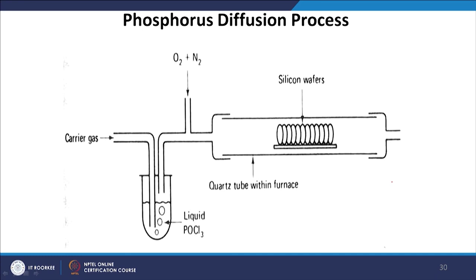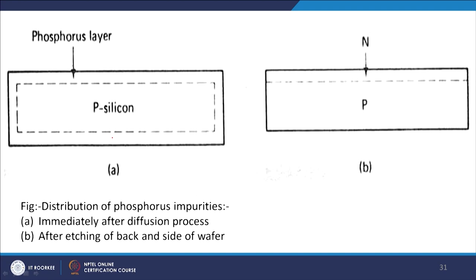After about 20 minutes, the phosphorus impurities override the boron impurity in the region near the surface of the wafer to give a thin, heavily doped n-type region. For a p-n junction silicon solar cell, the n-type layer is very thin and heavily doped, so that the depletion region extends inside the p-region. In the phosphorus diffusion furnace, the carrier gas containing liquid POCl₃ enters through one end together with small amounts of oxygen and nitrogen, forming a thin oxide layer containing phosphorus on the silicon wafers.